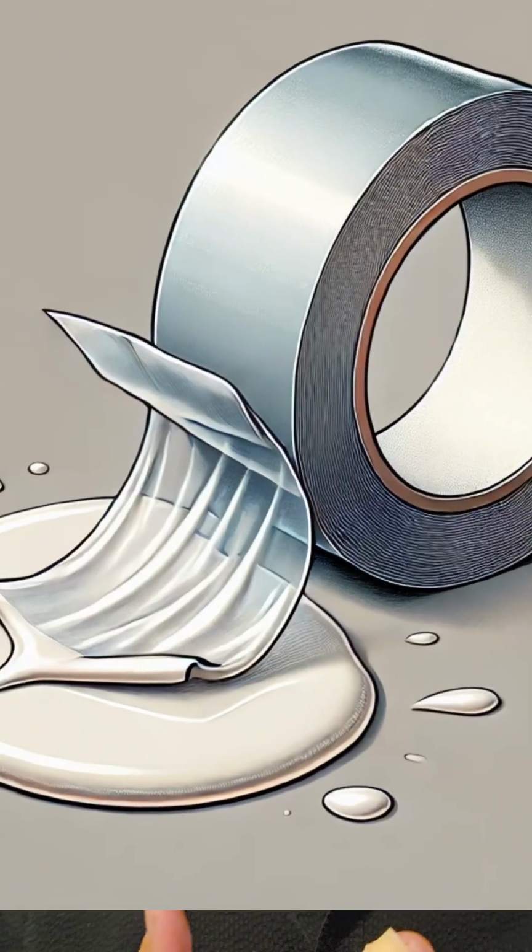Okay, so crack propagation. Think about the release liner when you pull it off of one of your tapes. That silicone layer is acting a little bit like a liquid, and it doesn't have the ability to dissipate force. There's no intermingling, there's no entanglement, and so there is high crack propagation. So really, when we think about things releasing, what we want to think about is crack propagation. In fact, every time something doesn't adhere, really what it is is a rate of crack propagation.